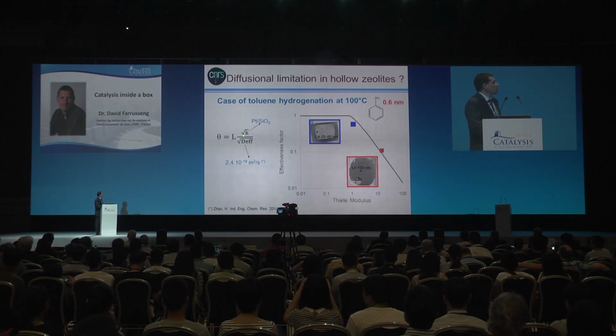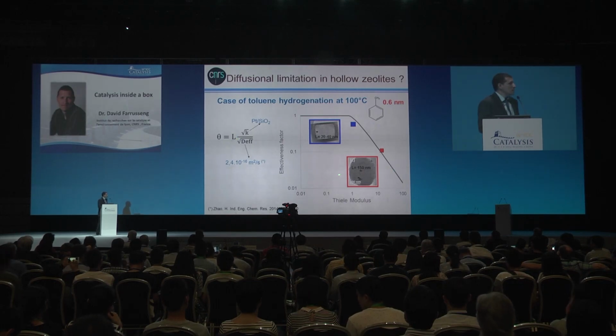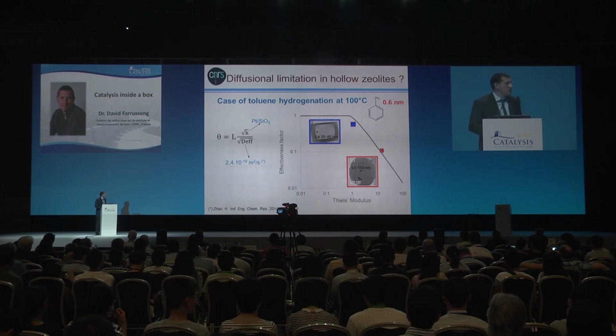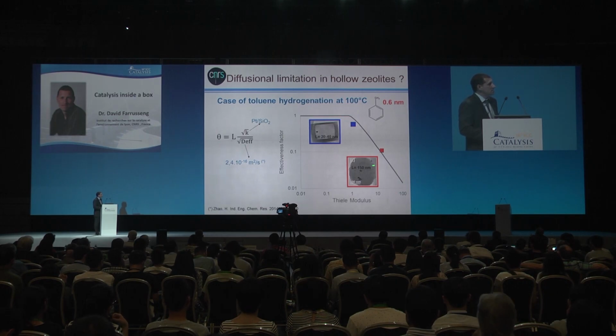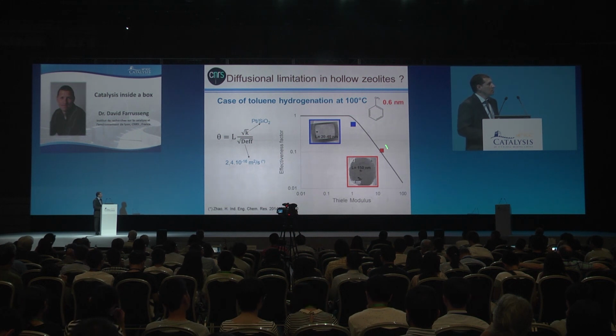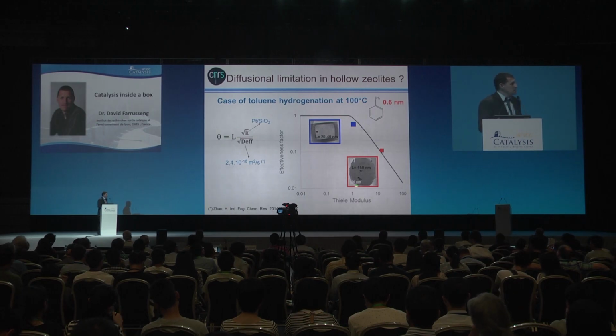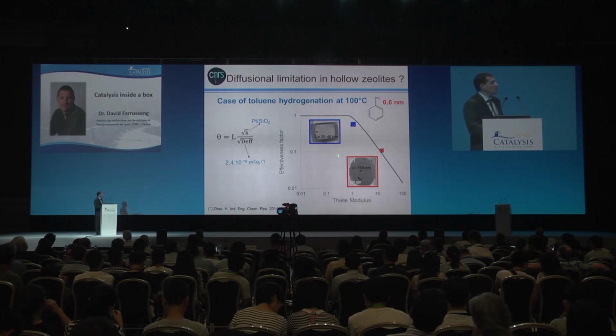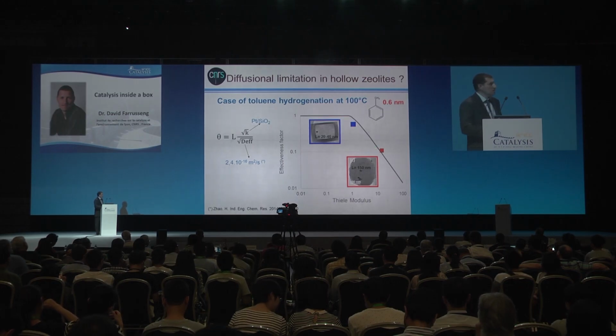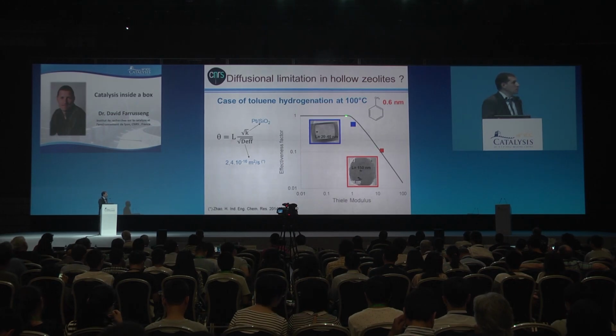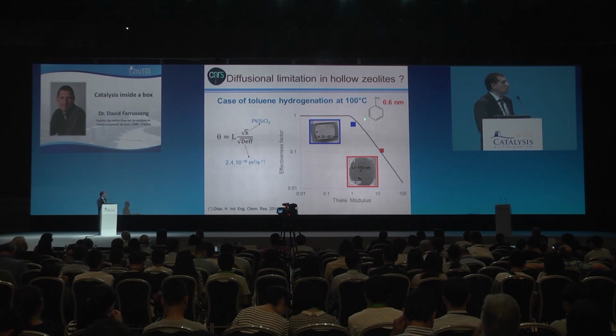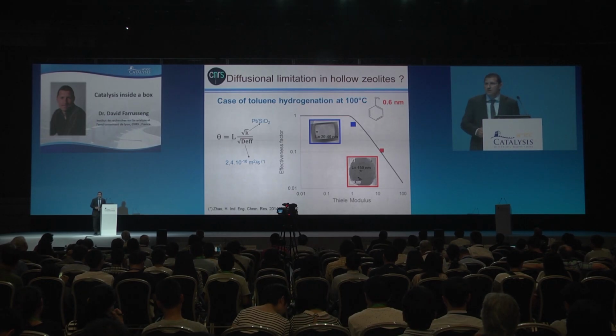The only parameter you can play with is the characteristic length. This is, so to say, the diameter of the zeolite crystals, or the thickness of the membrane. And in this case, you can see that for the platinum silicalite-1, in our system we have, let's say, one order of magnitude in this characteristic length, meaning that we can go from 10 to 1 here. We have plotted the points of the actual catalytic rate, and we see here that in our system we are hardly limited by the diffusion.